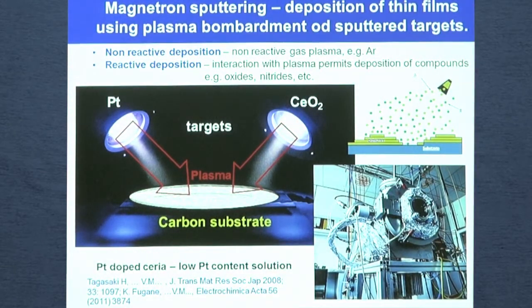We are using magnetron sputtering. This is a standard deposition technique, which can be used for non-reactive or reactive deposition. In magnetron sputtering, we have a target, and we are creating plasma by radio frequency or direct high voltage, and the ions of the plasma bombard the target and sputter off material from the target, and the material is deposited everywhere, so also on the substrate. And if the working gas is reactive, for example nitrogen, we can also produce compounds by reactive deposition. So this is the example of deposition of platinum and cerium oxide, because in our case we are combining the platinum with cerium oxide.